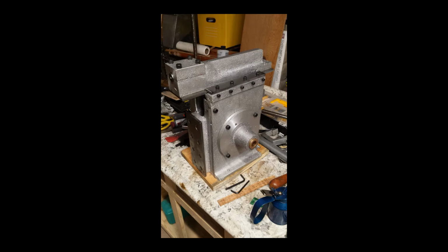I'm planning on getting into the same sort of thing, so stay tuned if you are interested and you can watch me learn. Things that could be done to improve this is definitely finer sand so that I wind up with a better surface texture, sand that is properly tempered, because the right moisture level is absolutely critical to make sure that you have as few sand inclusions as possible so the sand's not falling into the empty space and then becoming permanently bonded into the aluminum. Yeah, a few of those are never going to come out. But also a lot of it is just experience.